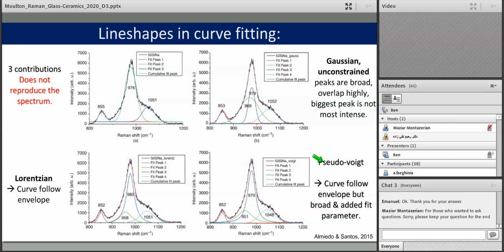Even though both are good fits, since in the pseudo-Voigt case you have an extra fit parameter, I would opt for the Lorentzian fit as the best fit because it has the fewest parameters that you modify and best reproduces the spectra overall. In general, this would be an okay fit.